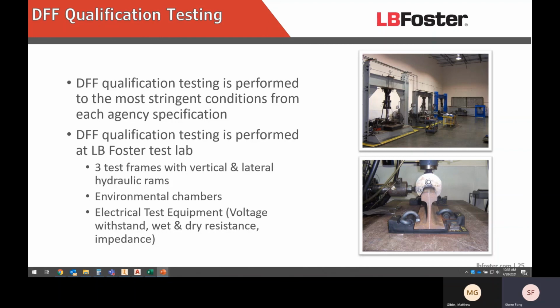We will run the qualification test in our test lab at Suwanee, Georgia. In our lab, we have 3 test frames with vertical and lateral hydraulic rams that perform the various loading conditions. We have environmental chambers to do the heat aging and different conditioning tests. And then we have electrical test equipment to perform the voltage withstand, the wet and dry resistance, and impedance testing.